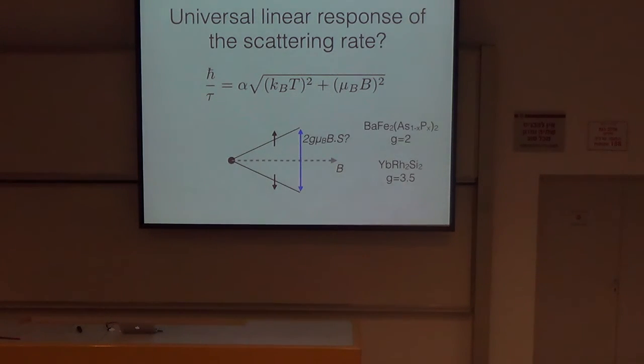So I tried to time it correctly, but anyway, the point is that my suspicion is that it's something to do with the Zeeman-like energy. I don't think this tells the entire story, but it certainly fits with some of the data. So if you just took out alpha from this relationship, then you just end up with the g factor as being the prefactor for this energy scale. Well, for alpha over beta equal to 1, that would suggest a g factor of 2. And the g factor of this material has been measured independently and it turns out to be 2.